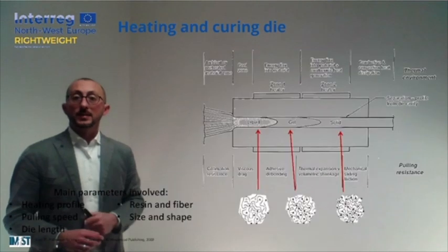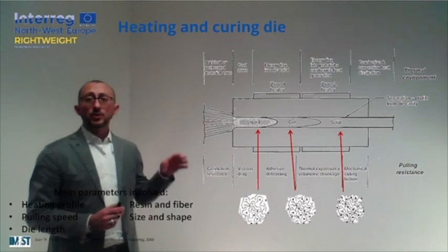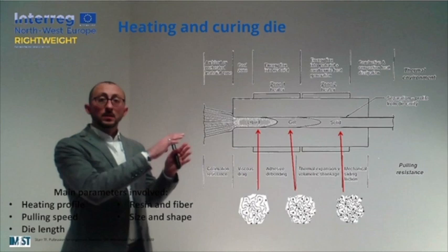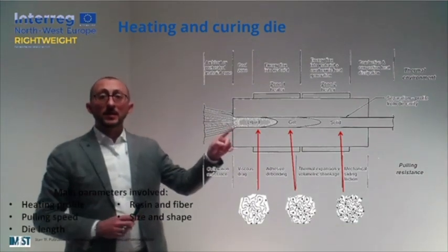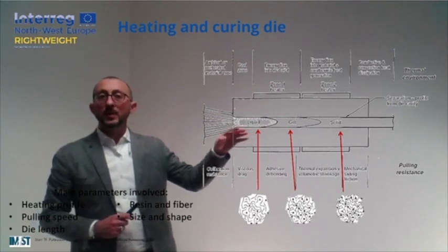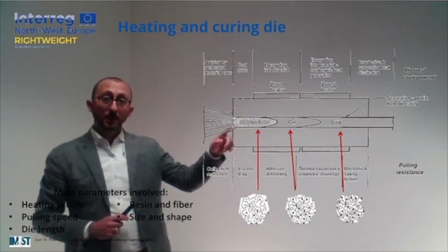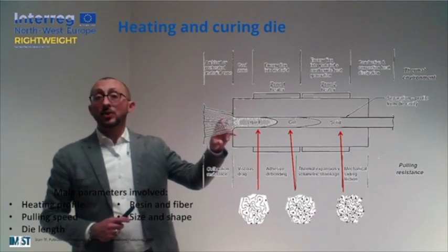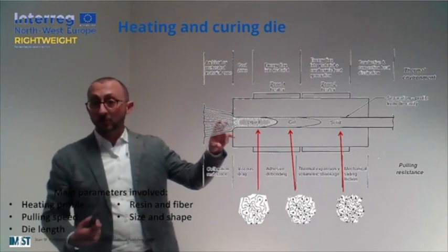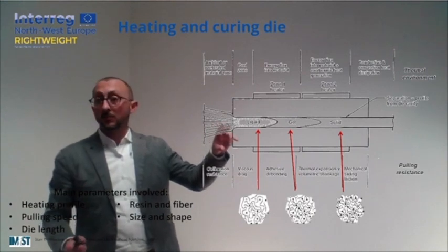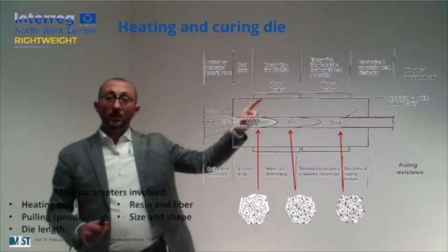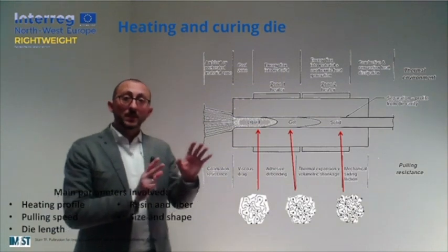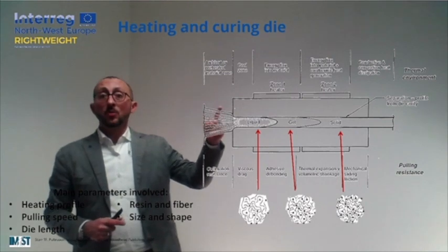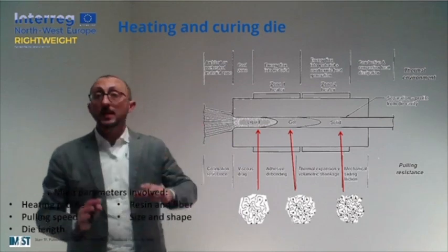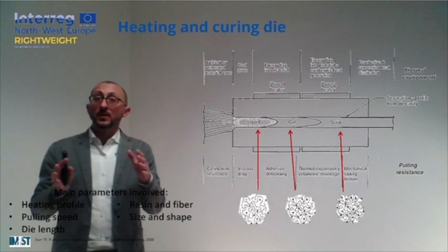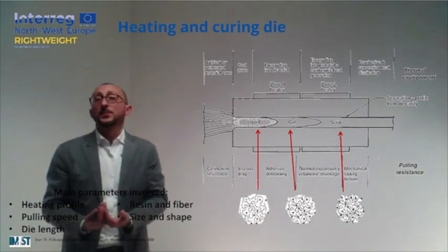So if we want to take a look inside the heating and curing die, we can imagine that something like this is happening. So the material is entering inside the die. At the very beginning, our resin is in liquid state, so we can think that here what we have is our impregnated reinforcement. The preliminary part of our die is generally at low temperature, because before the activation of the resin reaction, we want to be sure that the reinforcement is completely impregnated. So as you can see here, the heating system is moved a little bit away from the inlet, and in some cases it is quite common to have some cooling channels in this part of the die, just to keep the temperature at a good level and have some kind of a liquid zone that will guarantee the proper impregnation of the reinforcement.